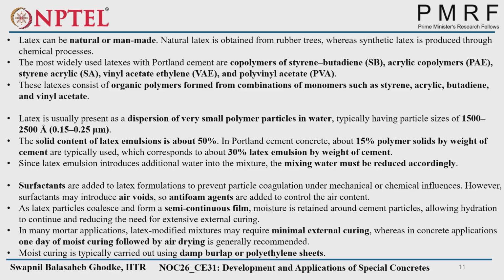We can reduce the water content because we are using latex, which has 50% water. Then, so that the polymers do not coagulate with each other, we have to use surfactants, which will disperse all the polymers into the concrete matrix. Then when we use surfactants, there is a possibility of air voids. To avoid a higher amount of air voids, we can go with anti-foam agents, which will control the air voids in the concrete.